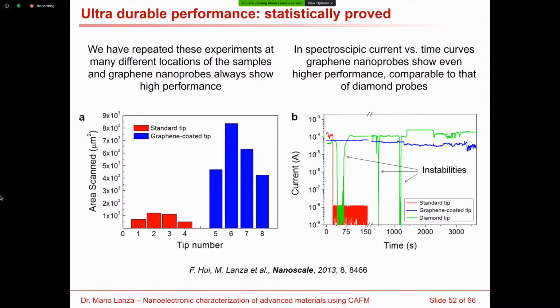In this slide, in panel B, I also performed a different experiment which consisted of applying constant voltage stress and monitoring the current over time for 3 types of tips: the standard metal-coated silicon tip, the standard metal-coated silicon tip with graphene on top, and one diamond tip, which is much, much more expensive.